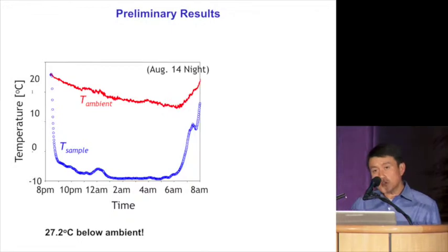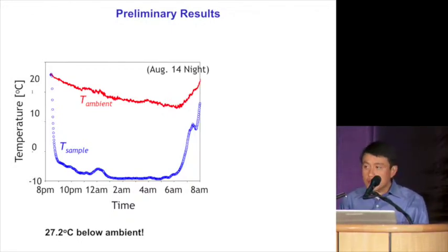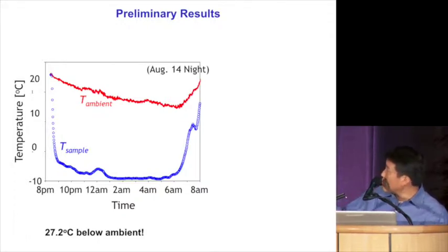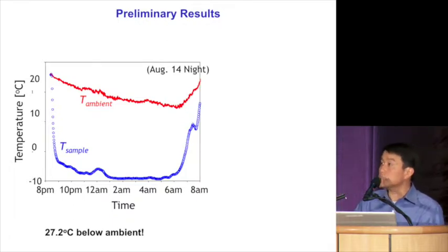Now, it will be interesting to put this experimental number in a theoretical perspective. And again, this is the theoretical curve that we drew. These are the ideal cases of a blackbody emitter and a selective emitter. So our experiment sits here, which compares quite well with what you expect from a selective emitter. We have some parasitic loss, and we're not an ideal emitter, so the temperature is slightly higher, but roughly speaking, it's on the curve.